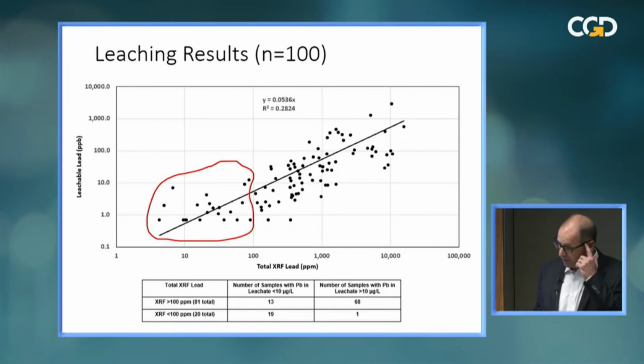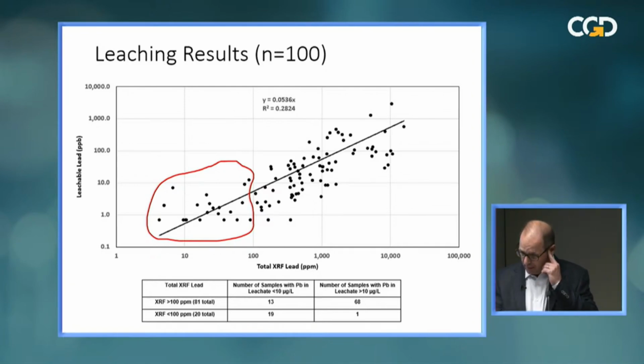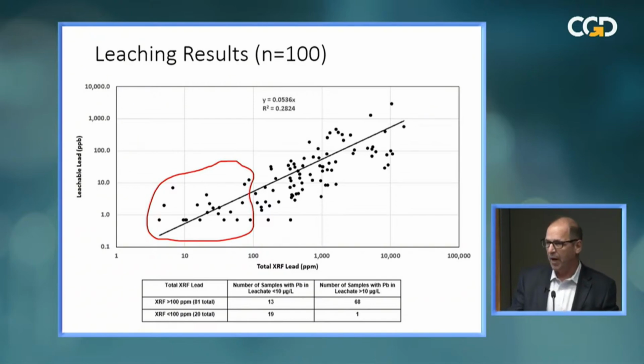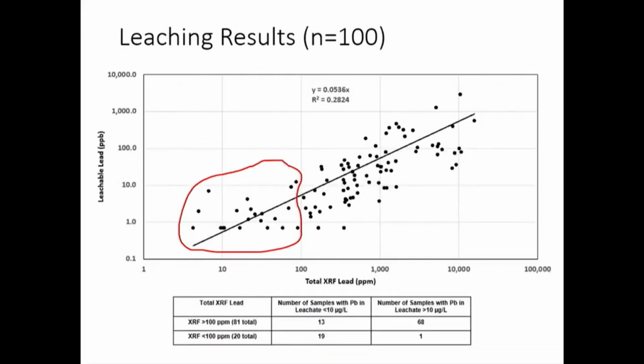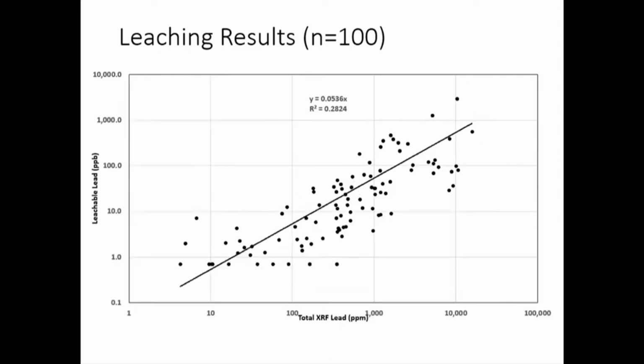I want to draw your attention to this part of the graph, which indicates that of the 20 pots that had less than 100 parts per million total lead, we only found one that leached above a drinking water standard. So in terms of a threshold, that's where we come up with our 100 part per million value of total lead being a good threshold for what could be a significant source of lead.